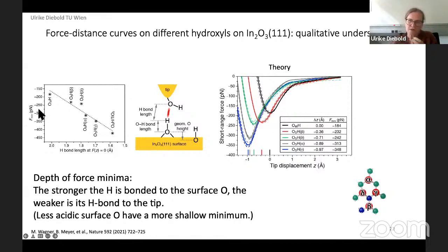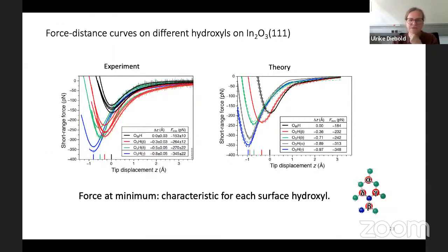So it turns out that when you have something that holds, it's like a tug of war. If the surface holds this proton very, very well, then you will not make a strong hydrogen bond. Then this is a shallow minimum. If it likes to give it off very easily, then there will be a more deep minimum. So this hydrogen bond between tip and sample is correlated with this minimum. Okay, so this is characteristic for each hydroxyl.